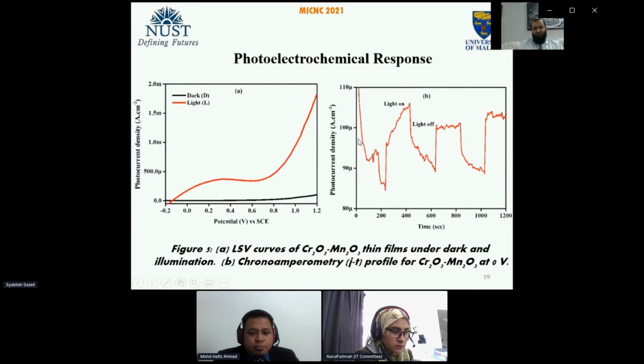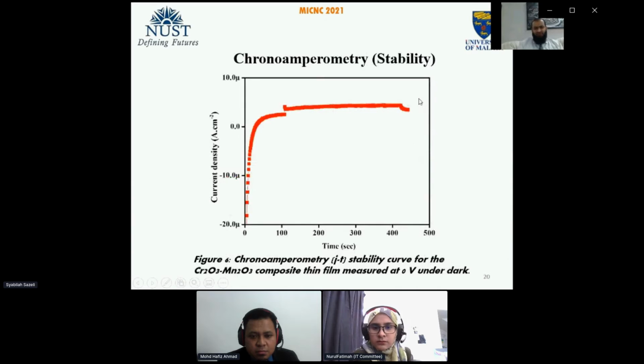Further, at 0 volt, the chronoamperometric response was confirmed by chopping in the presence of light and in the absence of light, and it shows that it is highly active even at 0 volt. Here we can see that even at 0 volt there is a difference in light and dark current, which is again confirmed by the chronoamperometric studies. Further, the chronoamperometric studies were performed for 500 seconds to confirm the stability of the material, and it was found that the material is highly stable for water splitting even at 0 volt, and there is no such decay in the current density.